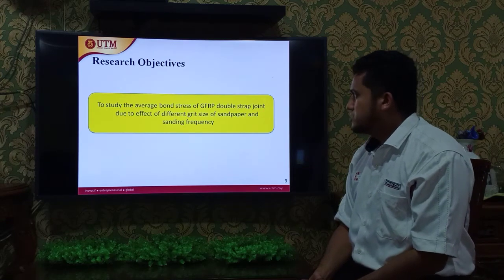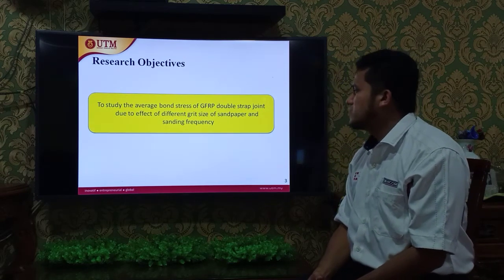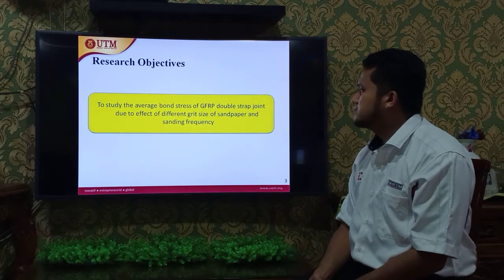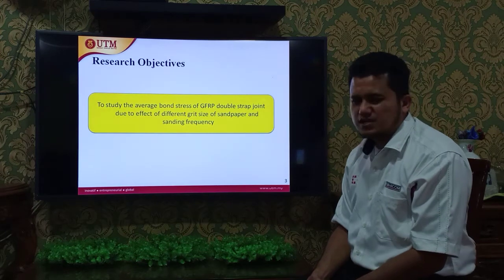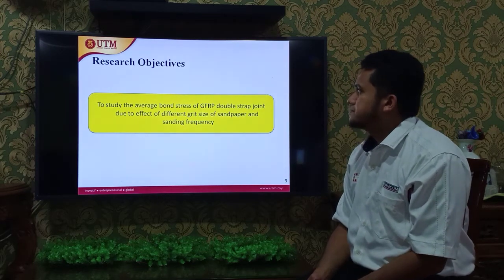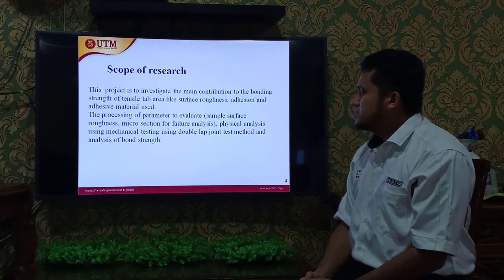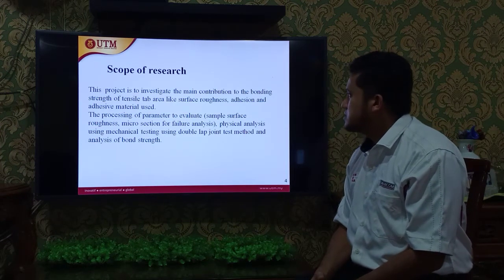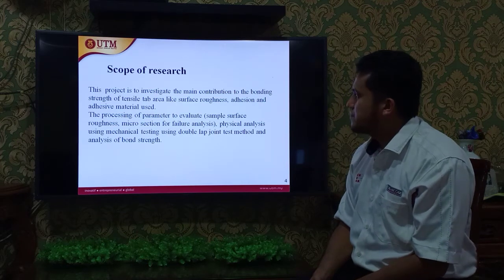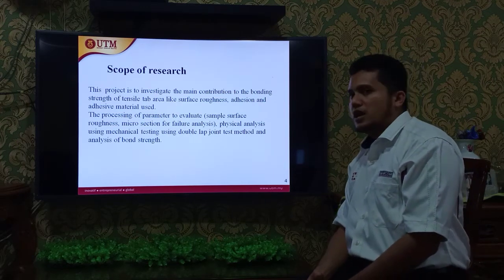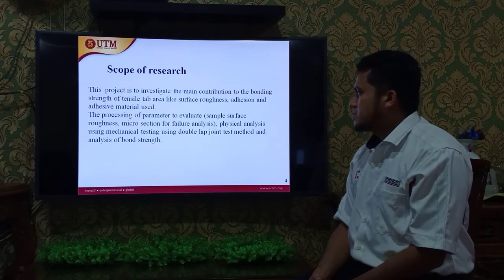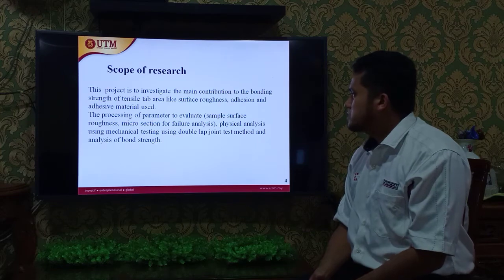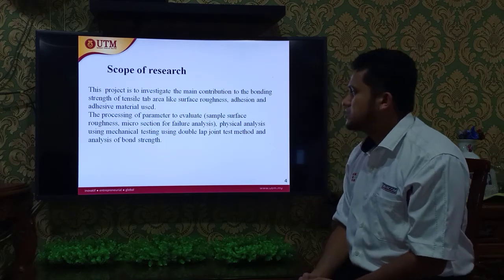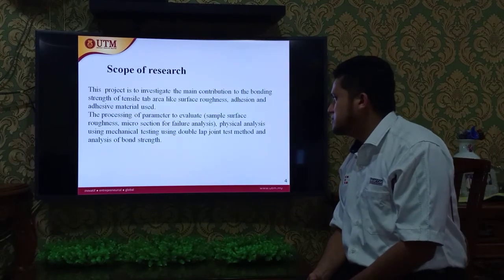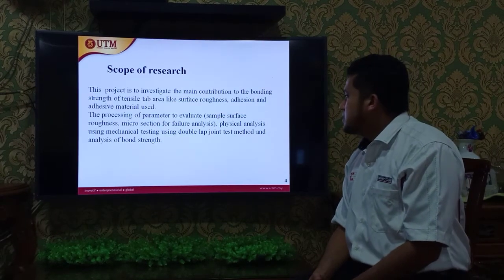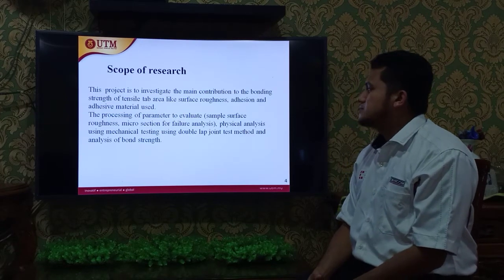This is my research objective: to study the average bond stress of a GFRP double lap joint due to the effect of different sizes of sandpaper and sanding frequency. For the scope of research, this project investigates the main contributions to the bonding strength of the tensile tab area, like surface roughness and adhesive material used. The parameters to evaluate are sample surface roughness, microsection for failure analysis, and physical analysis using mechanical testing, using the double lap joint test method and analysis of bond strength.